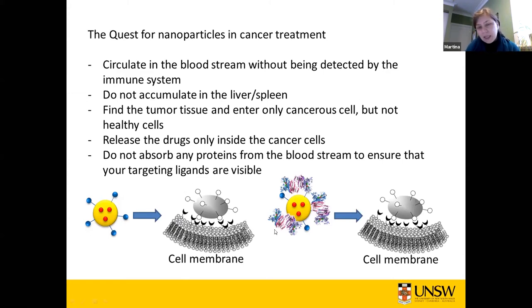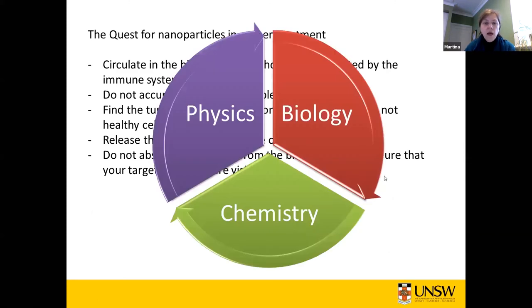In reality, if we're not careful and we don't design our nanoparticle very well, then these nanoparticles get quickly coated in the bloodstream by proteins. So just think about the blood. Blood has 7% proteins. The most common one are albumins, but there are tens of different proteins here. So depending now on what absorbs on the surface, you change the properties of these nanoparticles quite significantly, and it really might decide the fate of your nanoparticles. So it basically shows it's a very, very complex problem.